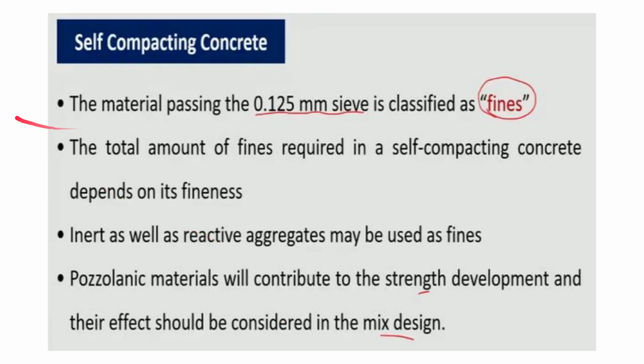Here, in the case of sand, we use a term called fines. How it is different from fine aggregate is that fines is basically the material passing through the 0.125 mm sieve. Fine aggregate, in geotechnical classification, is anything less than 4.75 millimeter. But in SCC, we denote fines as any material passing through 0.125 mm.